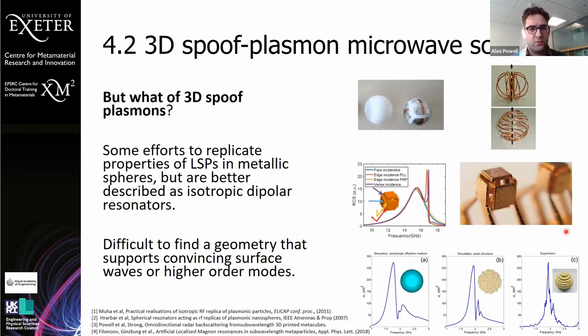So the question I'm asking in this section is, what about 3D spoof plasmons? What can we do with them? And there's been a few efforts to create these properties, but most of these only really work in the dipolar regime. And even then, for many of them, only at specific angles and polarizations. So there's been some studies trying to make these, two of which are essentially just crossed dipoles at right angles with caps on the end that give them a lowering of the frequency, and an increase in the scattering power, so you can see them more easily. These wire structures try and create the surface impedance that would be present in a dipolar resonator. It's not really convincing that any of these can argue that they're actually replicating plasmonic properties in the microwave. And this is all the approaches in this field that I'm aware of so far.